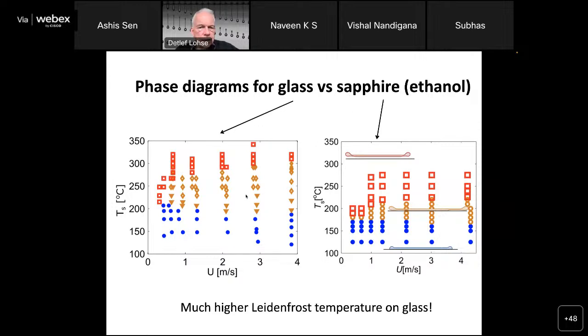And what you see is that for glass you achieve Leidenfrost only at much higher temperatures. So here typically we have 300 degrees Celsius, whereas on sapphire you already have a Leidenfrost effect at 220 degrees Celsius. So it's a huge difference. And the difference is, of course, that the heat conductivity of glass is much, much worse as compared to the sapphire case. So the droplet falling on the substrate partially cools, and this is seen here, whereas for this perfectly conducting case, it is not seen here.